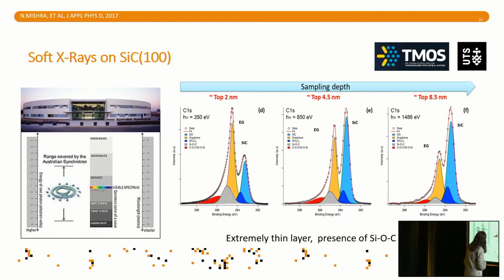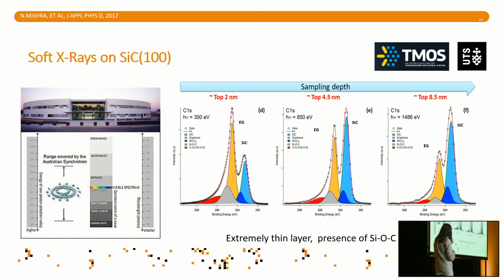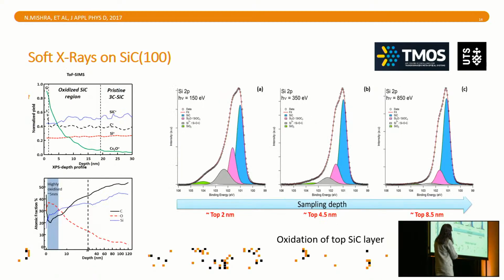So that's a good start. We did, of course, a lot of characterization along the years. Soft X-rays has really helped a lot also to understand thicknesses, and to clarify the fact that we have some oxidation just underneath the graphene. So the interesting thing is that we grow the graphene directly on the silicon carbide. The catalyst can be removed because they are in liquid phase, we remove that by wet etching and sonication. But underneath, we have some oxidation of silicon carbide. So this will come back.